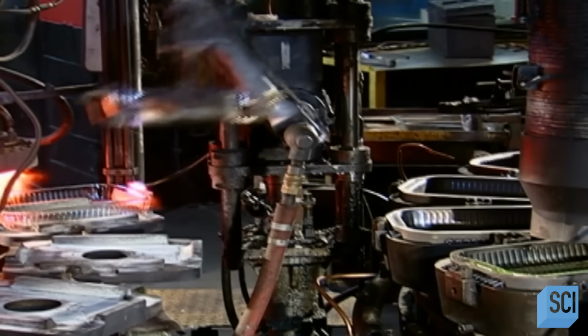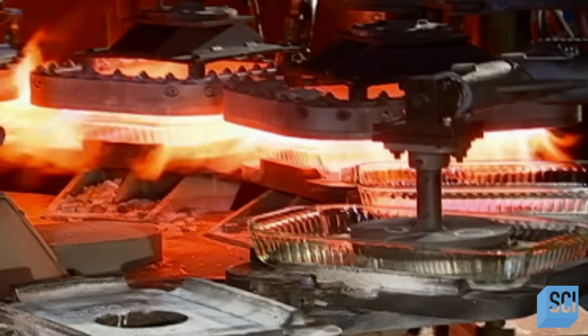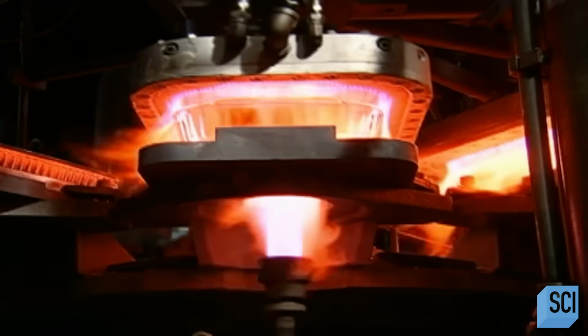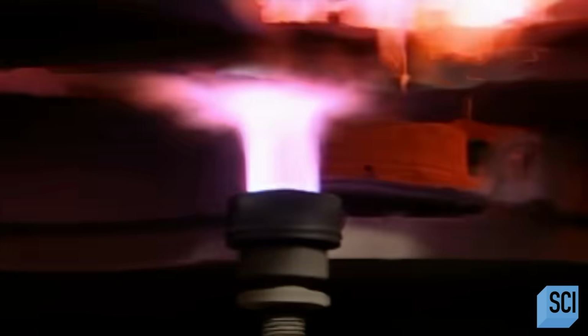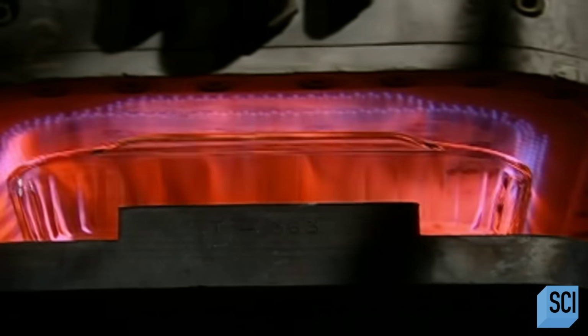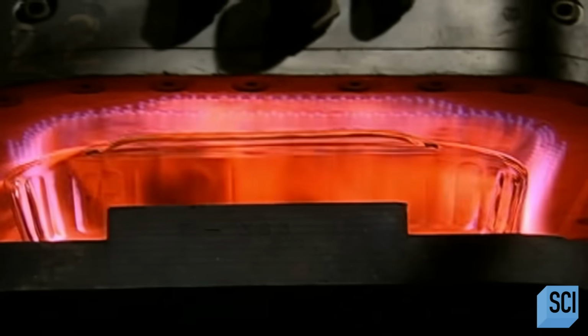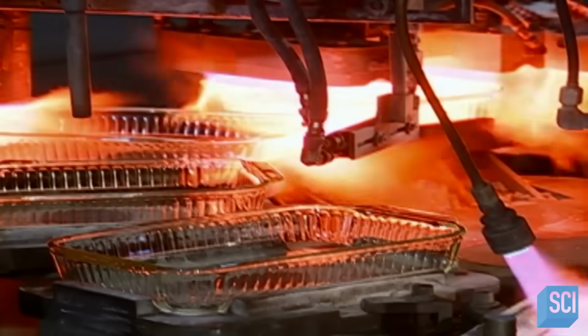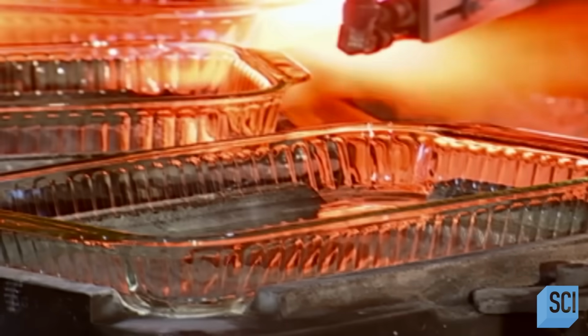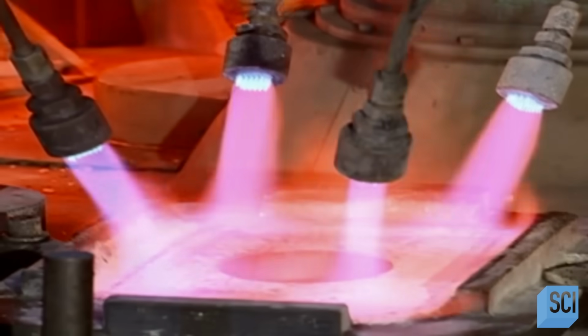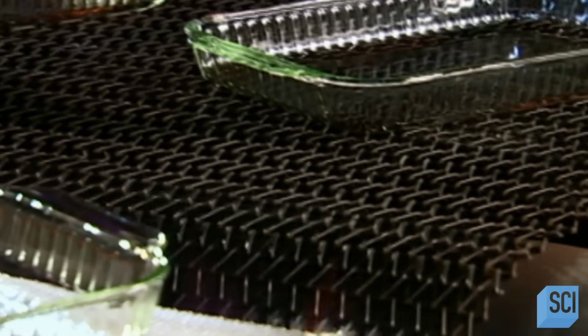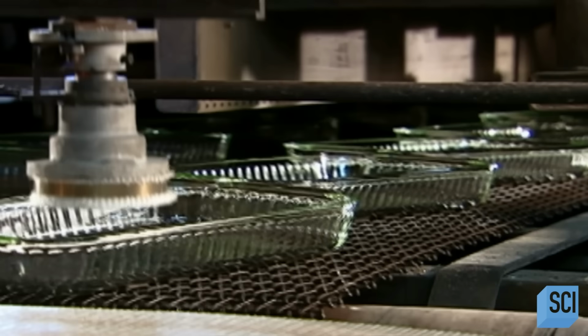A mechanical arm suctions up the glass dish and sets it down on another revolving table. Flames lick the glassware from burners above and below. The dish is exposed to a temperature of over 1,800 degrees Fahrenheit. This softens its sharp edges so that the rim is smooth. Next, hoses blast high-pressure air, cooling the dishes to solidify them, so that a mechanical arm can pick them up without ruining them. It transports the glass dishes to a conveyor belt. Further down, another arm feeds the dishes to a kiln, where heating and cooling cycles temper the glass. This is what gives Pyrex its strength.